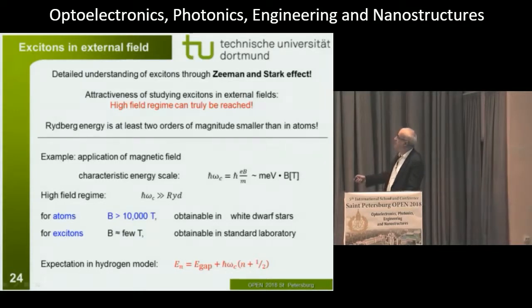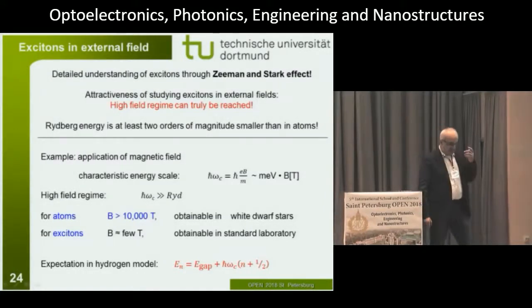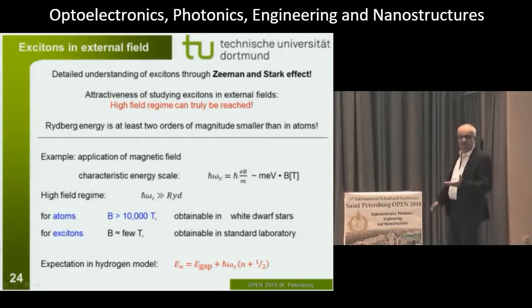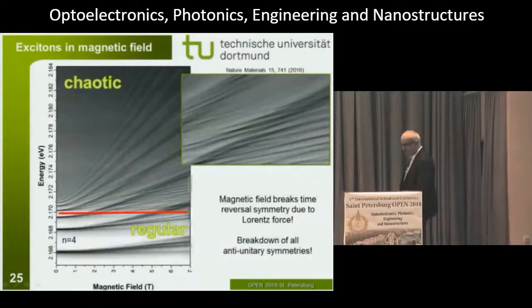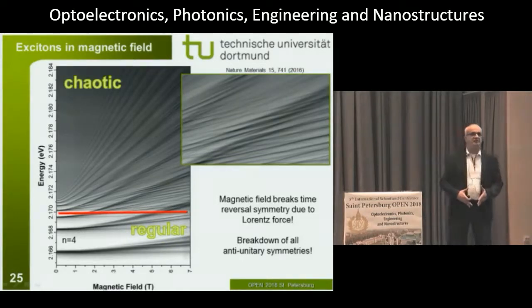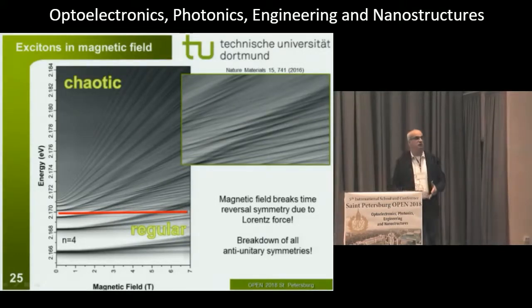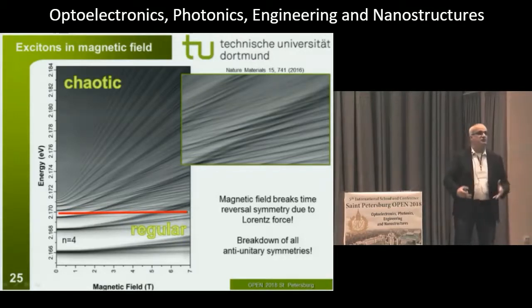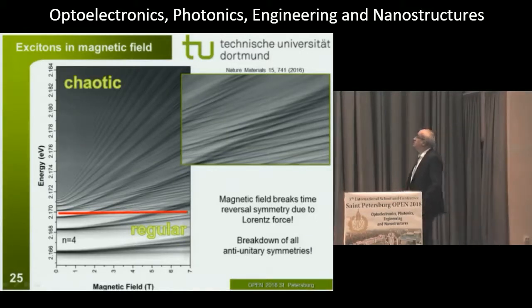And in this particular regime, where magnetic confinement is much, much stronger than Coulomb interaction, the expectation is that you just observe Landau level transitions. And this was also our expectation. This is the result. I have to give credit here to the PhD students. This contour plot may look trivial, but in fact it's composed of 12,000 spectra in order to get the proper resolution. So the PhD students were locked for 4 weeks in the lab. They got some food from time to time, but they were recording this series continuously in order to get this contour plot. What you see here is starting from n equals 4.